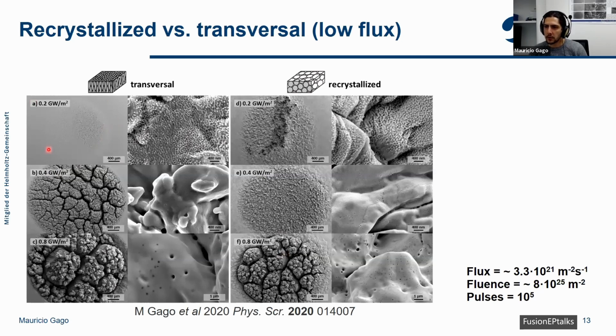So here, one interesting thing to observe is that at the lowest power load, we have almost no surface modification for the transversal sample, and we have a much higher surface modification for the recrystallized sample. This I will explain to you at the end of the presentation, because it has to do with some other phenomenon that we will see. But once we applied 0.4 gigawatts per square meter, we see that the recrystallized sample actually has a higher resistance, at least in this case.